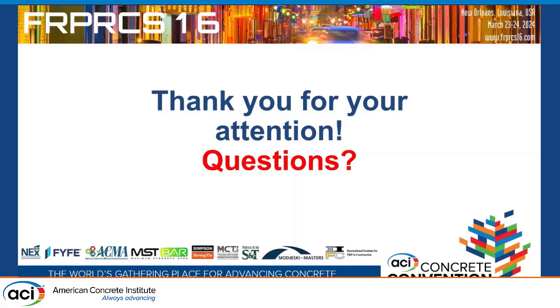Pete Renshaw, Pultron Composites, New Zealand. Have you looked at the relationship between the compressive strength and the interlaminar shear strength? Because looking at this, it seems that it lets go by splitting, which is obviously a function of interlaminar shear. We have not. I would say in ASTM D695, because there is no clamping, the splitting was very obvious, and that was our judgment for providing some clamping, but we have not studied that.